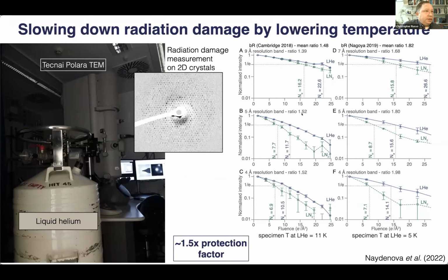It's somewhere between 1.5 and 1.8 times a reduction in the damage to protein specimens at liquid helium temperatures versus liquid nitrogen temperatures. And that will allow us to do even better in terms of this extrapolation back to 0 dose, and be able to determine the structure of molecules that are even smaller than we can do now. So I don't think we want to leave this behind. So that's our next thing.